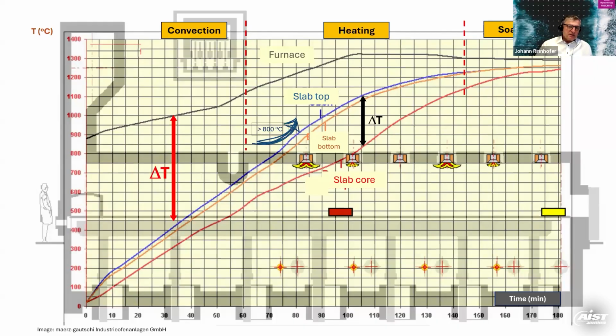So scaling is bad on the one hand. On the other hand, it's good because you're healing surface defects on the steel, which is sort of exposing virgin steel again, which is a good feature of scaling. So it's not only bad, it's also good. So this is how it looks. We are heating such a billet of 200 mil in a time period of approximately 180 minutes. So this is just an indication.